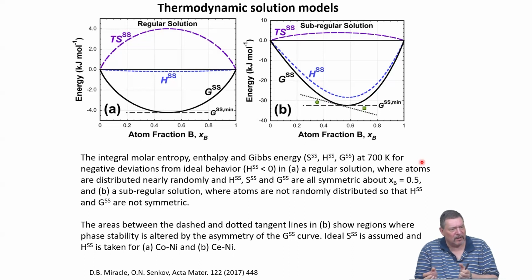And if you say, there is some interaction, like for example, if I mix one atom into another, maybe heat is generated, or maybe the volume changes from the way you macroscopically calculate, then a regular solution model is applied, which has an interaction parameter in enthalpy and not in entropy.